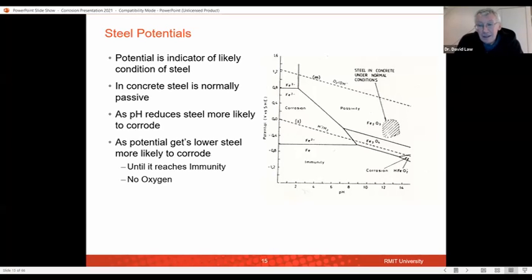And while I'm here, just to mention, you've got this area of immunity. And you can see these are at very low potentials. So when we have a steel potential and it's passive, it's generally in the region, say, minus 100, 200 millivolts. When we move into the active corroding region, we're moving down into lower millivolts, which are generally 300, 400, 500 millivolts. But if we get to very low potentials, we actually get immunity. And this is what we do with cathodic protection that I'll come back to at the end.